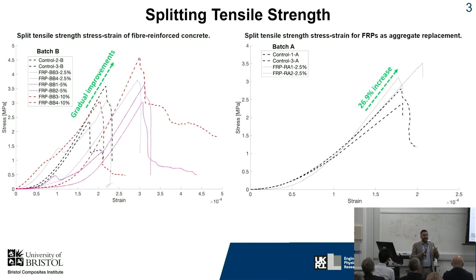The more fibres you add, the better the mechanical property in terms of split tensile strength. It's worth mentioning that split tensile strength is a well-known mechanical test for concrete. Batch B is one of the key findings in my project, because the majority of the literature proposed a reduction in some elements of split tensile strength. So now we have a win-win for batch A and B.